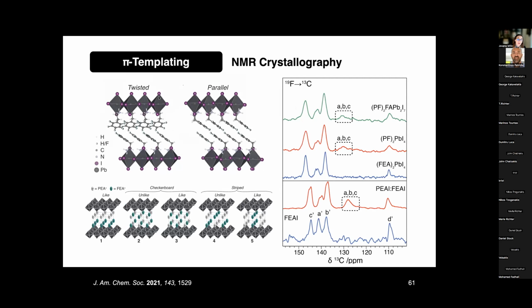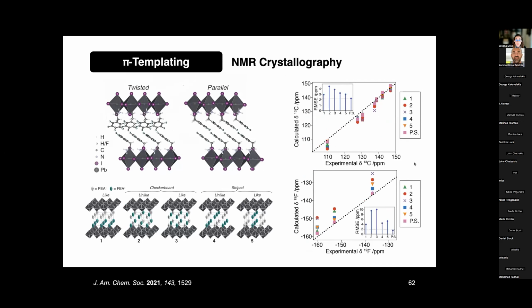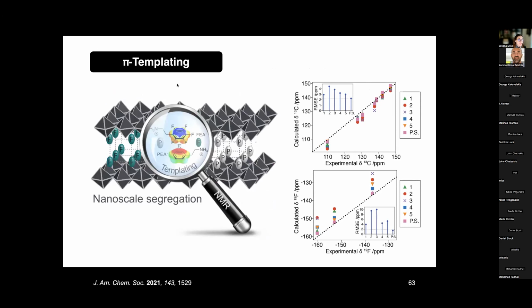are identified in their crystal structure, ultimately revealing a linear correlation between the calculated and the experimental data in the case of the chemical shifts of both carbon and fluorine, with the closest match of the theoretical assembly to the experimental structure being that of structure 1, this fully alternated system that is also found to be most thermodynamically stable. But in fact, the most accurate match, within an accuracy of about 99.9%, is the one that corresponds to the mixtures of neat phases, suggesting that indeed these systems, especially in thin films and mechanosynthetically prepared powders, are in fact nanosegregated, meaning that they preferably form alike structures that remain in nanoscale contact, leading to these cross-polarizations, which really challenges the previous reports and opens a broader perspective on the role of this pi templating in these materials.